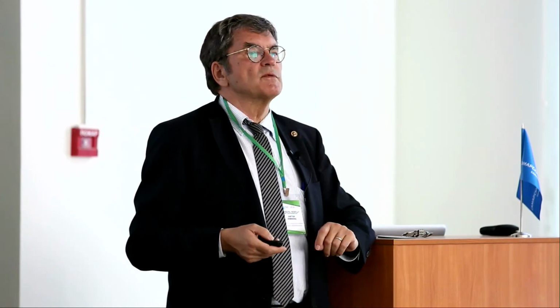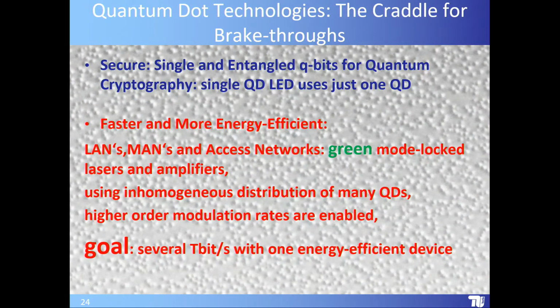At this point, I will switch the subject from one quantum dot to many, many, many, many, and switch to local area networks, metropolitan area networks, and access networks. And I will show you that quantum dot lasers present the basis for green, which means energy efficient lasers. Today only lasers, not amplifiers, using the inhomogeneous distribution of many quantum dots. And I show you a little higher modulation rates, and the goal is now several terabit per second with one single energy efficient device.